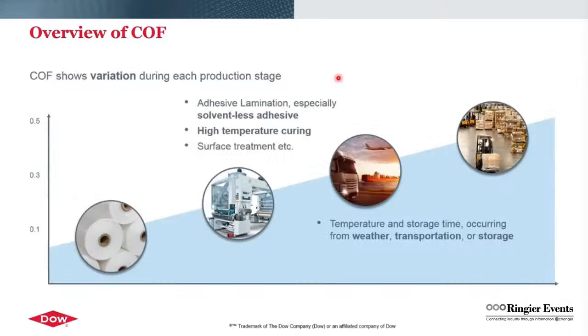The COF of a packaging film or laminate may vary as it undergoes various processes, such as during adhesive lamination, especially with the use of solventless adhesive with high temperature curing and surface treatment. The COF may also vary after the film roll undergoes storage in the warehouse or transportation after some time. The COF variation may be accelerated by high ambient temperatures, which could be weather dependent, and this is beyond the control of the converter. So next, let us look at how to resolve this issue.